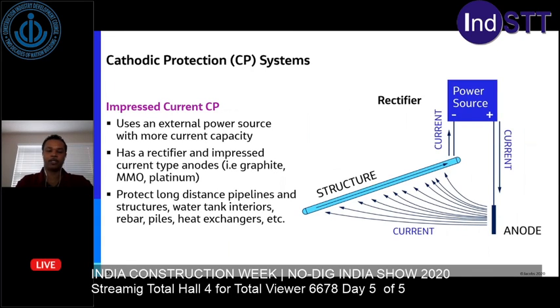And you can go with the impressed current CP system if you need a larger current capacity. You will use an external power source from the power company. You need a rectifier as well. Some of the impressed current anodes you would use would be the graphite type anodes, mixed metal oxides, or platinum type anodes. And there's others like high silicon anodes that can be used as well. And this type of CP system is designed to protect those long distance pipelines or those larger structures, also water tank interiors, rebar structures, piles, heat exchangers, and there's a multitude of applications for these impressed current systems. Next slide.